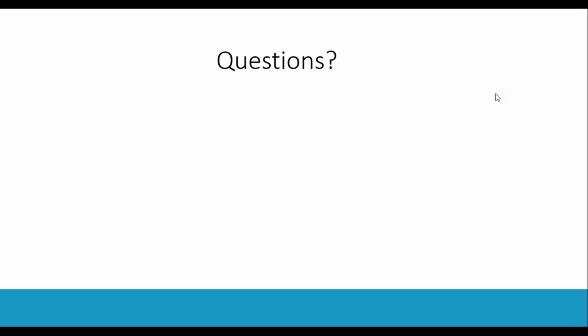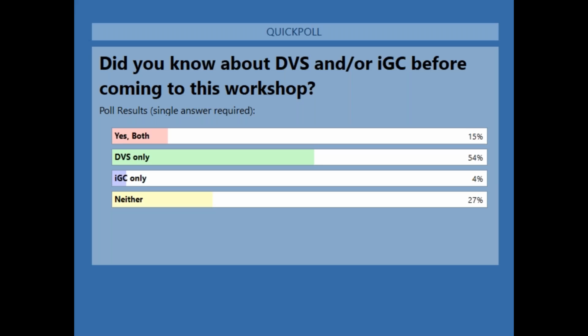To answer that question, it depends on the composition of the sample itself and the amorphous content. When I'm working with a composition, what I'm measuring is not the uptake of every single component, but the sum total of the components. So if the material contains a lot of components that form hydrates, that could have a massive mass uptake, which could cover a potential mass drop. However, if the amorphous content in the sample is high enough, then the mass drop will still be evident.